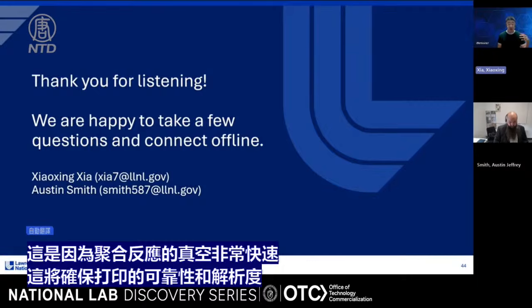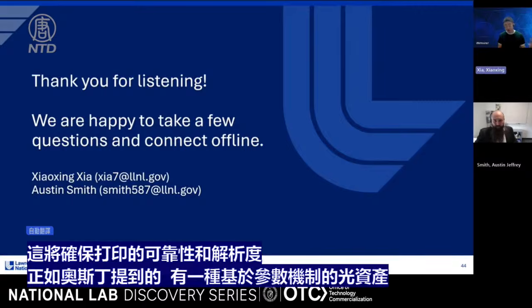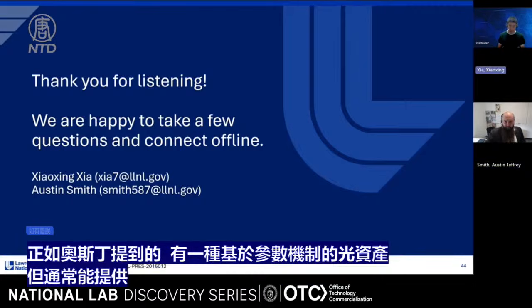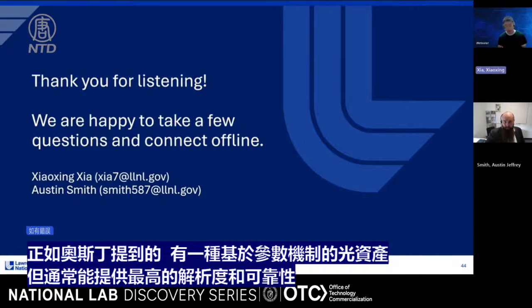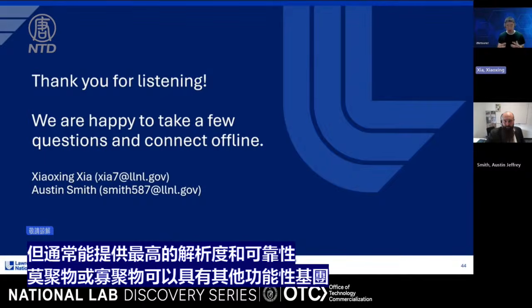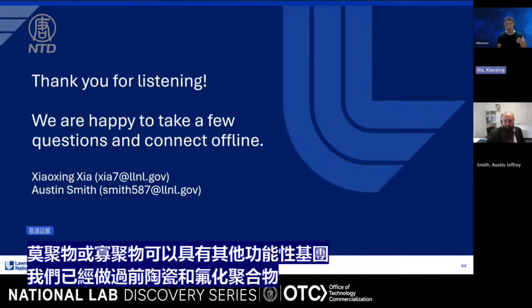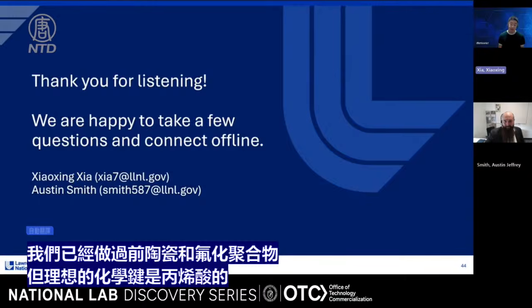And as Austin mentioned, there are photoacid and photo-base polymerization mechanisms, but generally acrylate gives you the highest resolution and reliability. But the monomer or oligomer can have other functional groups. We've done pre-ceramic, we've done fluorinated polymer, but the chemical bond ideally is acrylate.